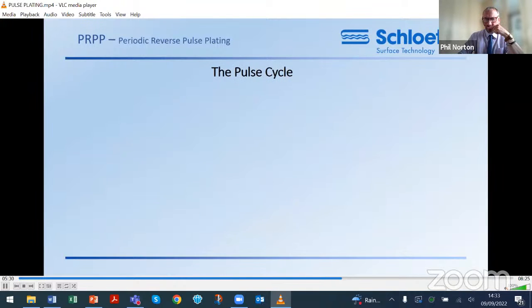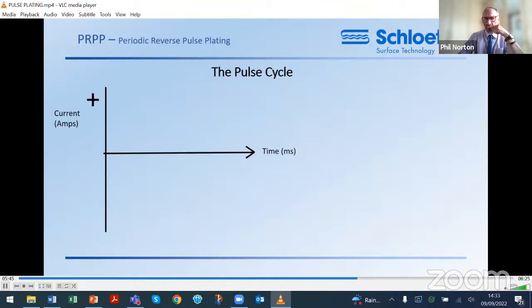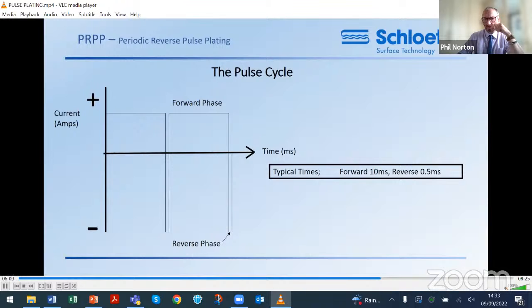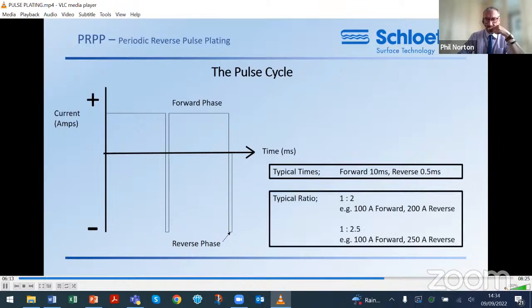Let's quickly look at some of the terminology used when describing a pulse cycle. The two main elements involved are time, measured in milliseconds, and current, measured in amps. The current is either positive, as in normal DC, direct current, or negative. A cycle comprises a main section of DC plating followed by a much shorter pulse of reverse current. For the CU110 system, the forward phase lasts 10 milliseconds. The reverse phase lasts 0.5 of a millisecond, but is typically twice as strong as the forward phase. This is where the ratio terminology originates. For a ratio of 1 to 2, the reverse will have twice as much current as the DC phase. Ratio can be anything from 1 to 1 up to 1 to 12.